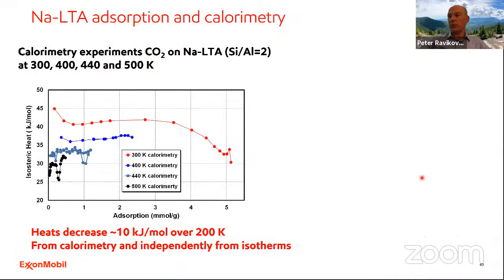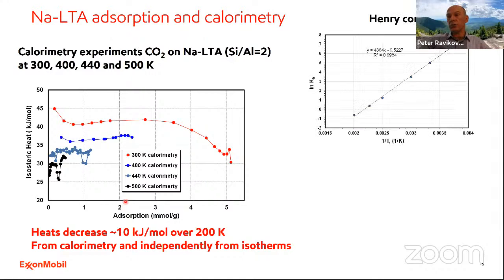This is another experiment. We took another cationic zeolite, and we did the calorimetric experiment. And in this case, it's even more prominent. So you can see calorimetry at 300, 400, 440, and 500 K. There is a clear temperature dependence. So to double check this, we independently calculated the Henry constants. So we fitted the Henry constants of the measured adsorption isotherms, now just adsorption experiment.